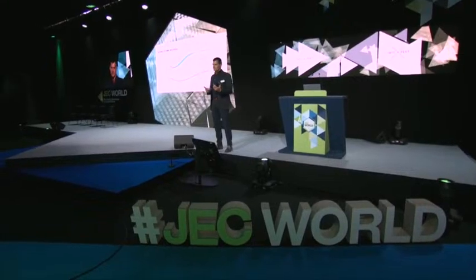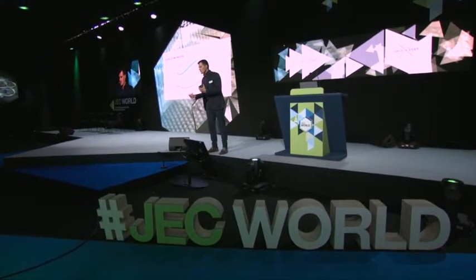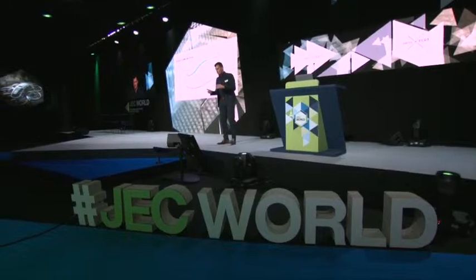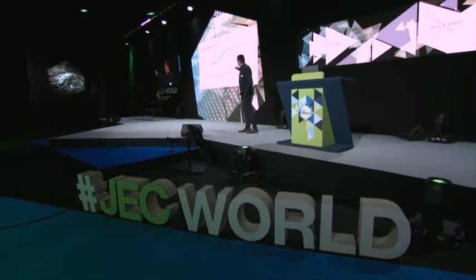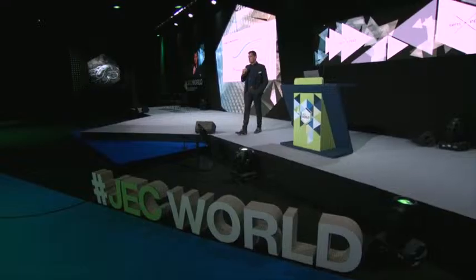And if we use different batches of material and we are aware that the viscosity is changing and the cure behavior is changing, we can adapt the process in a different way. Because what we could see here from this picture, the older the material, one conclusion could be the faster I can produce my parts. But be careful. We see that the viscosity is changing as well, and I have to entirely fill my cavity to get a good part out of that. So I need to know how my material behaves, not to be in danger with all the material deviations that can occur, that I produce scrap parts at the end.